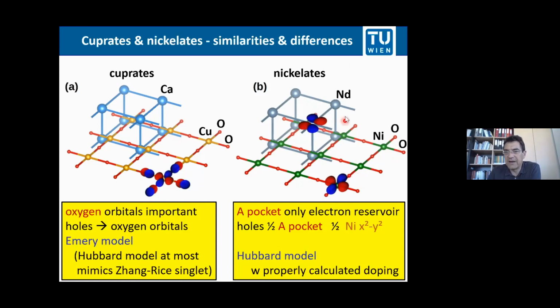And then here you have the Nd A pocket, that is the Nd xy orbital. And 50% of the holes go here, 50% of the holes go here, but it's on another plane and it is not hybridizing. So it is like an electron reservoir. You only have to properly calculate the doping. Here are actually the orbitals as they come out of a Wannier function projection. That is the orbital going with the A pocket, and that is the orbital going with the gamma pocket. That's the z squared orbital, which can more strongly hybridize with the nickel z orbital. Okay, so that is the situation. So we have a one-band Hubbard model plus an electron reservoir.